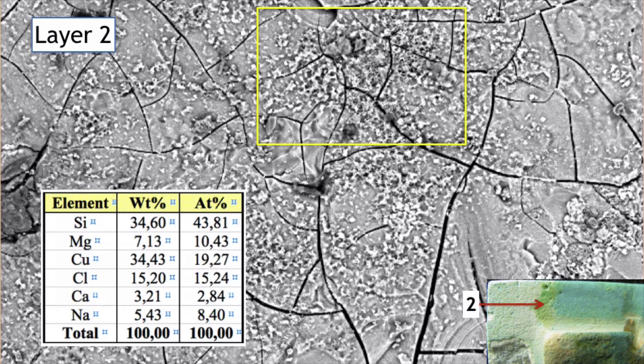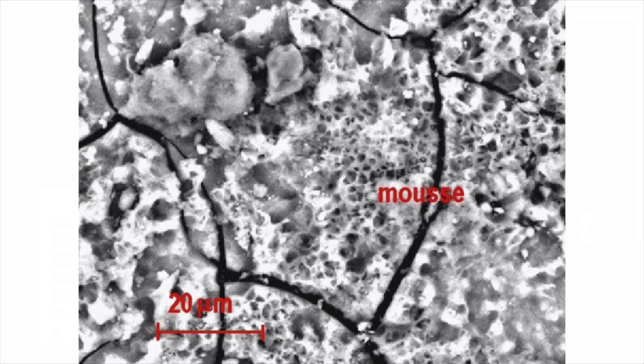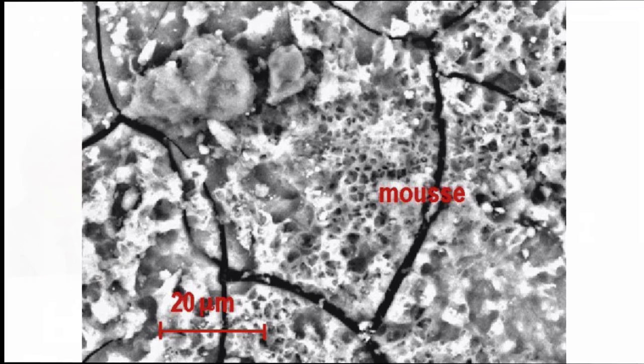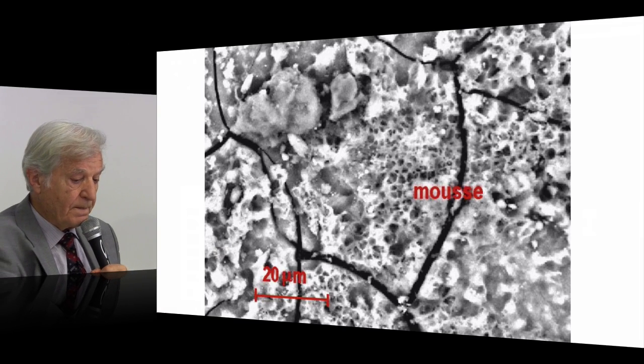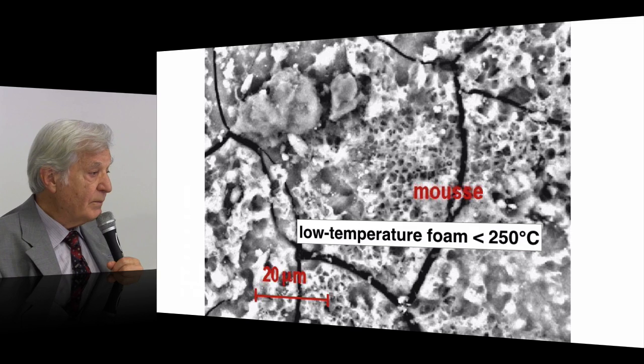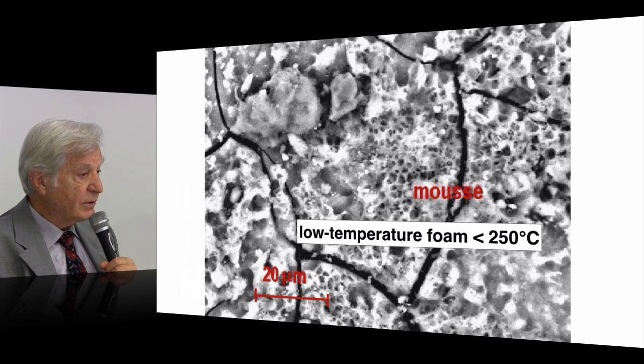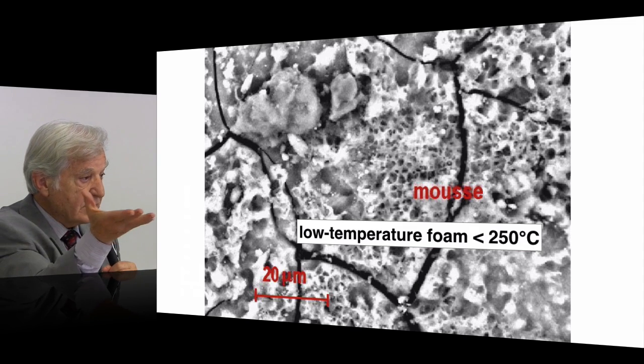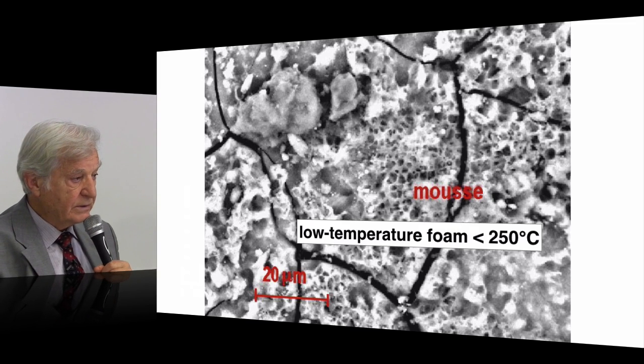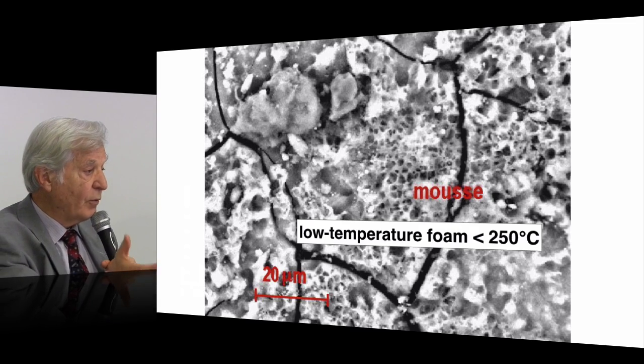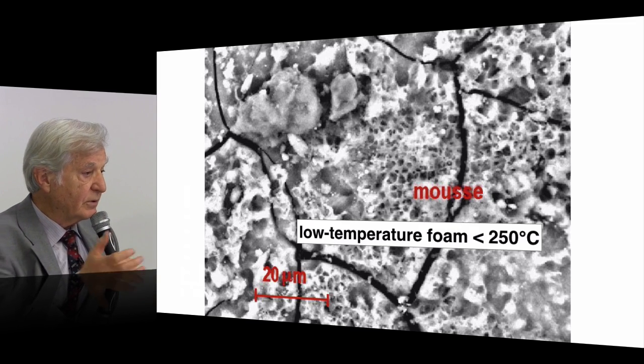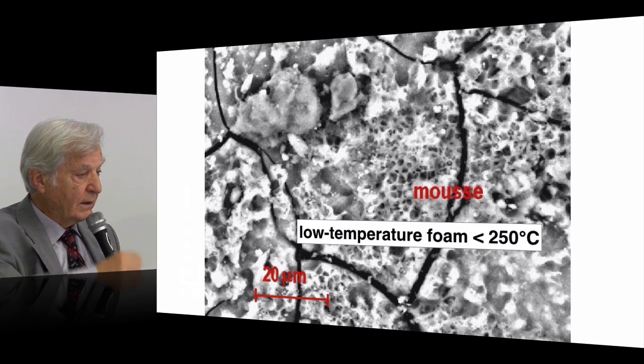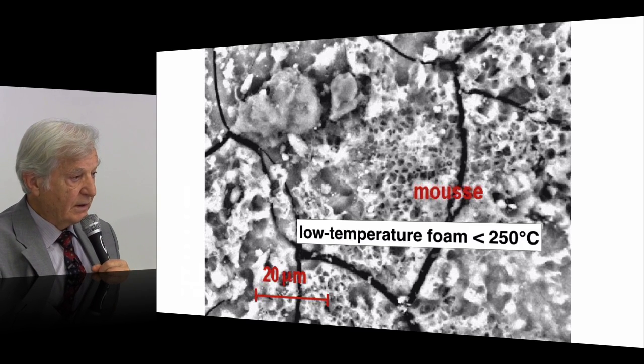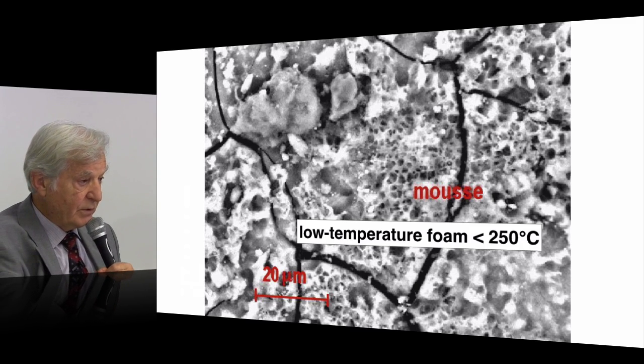And then we made a close-up and found that it is expanded. It is a foam. It is a foam that results from the dehydration of the material. It is a water-based silicate that contains the geopolymeric reaction, and we know in the lab we make our foam at 200 degrees C, 250 degrees C. The water vapor wants out, there is softening of the matrix, and you create a foam. This is what we have, a foam.